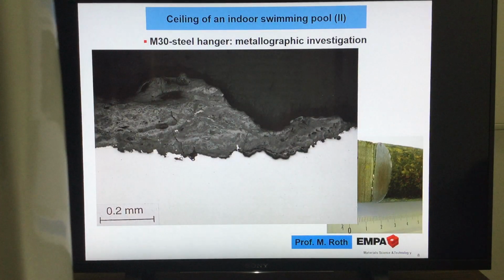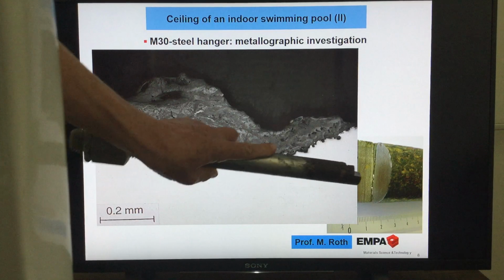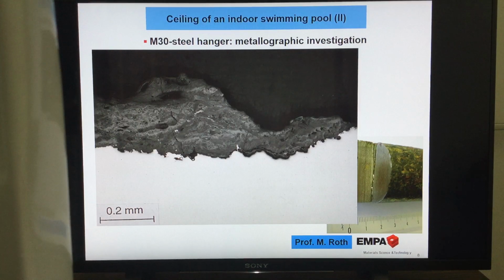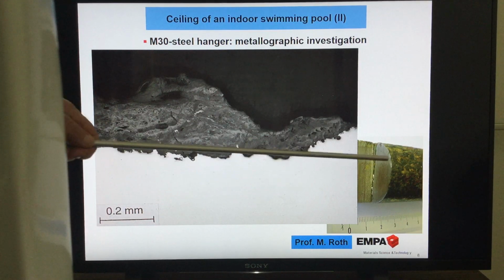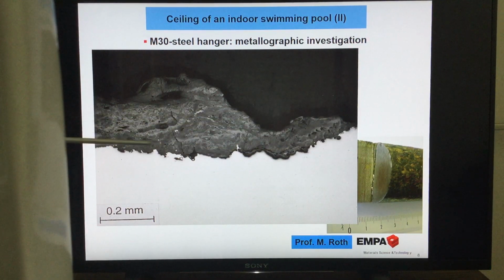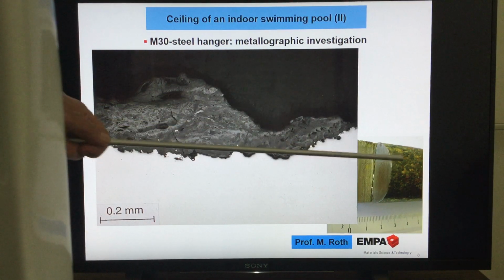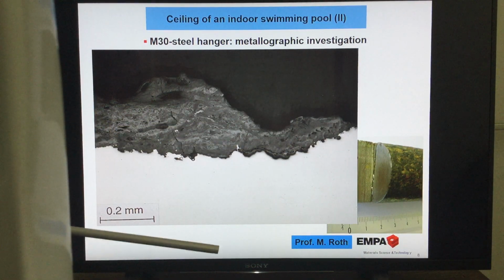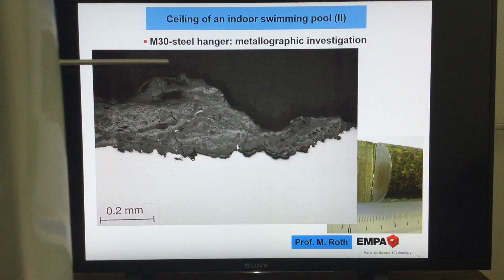But now the next step is coming, and this is shown here, that we made this cut inside the material where it was heavily corroded, and we see already our metallographic specimen. In the metallographic specimen, this white part is the iron underneath. And that part which we see here, this is our corrosion layer. It's not equal, it's a little bit higher here. Now, that is the most important image.